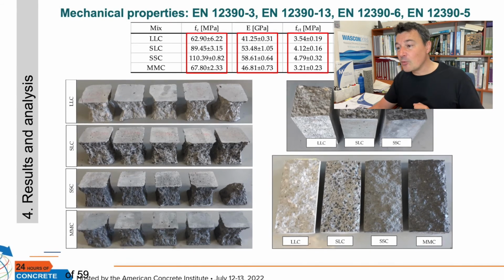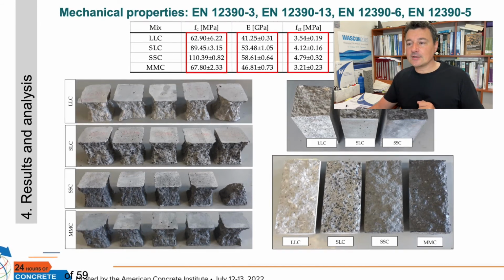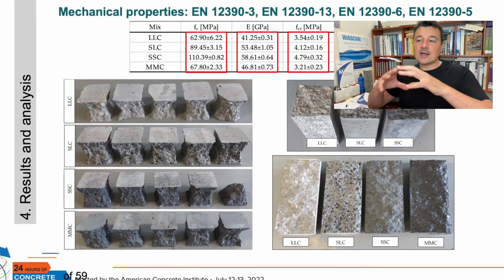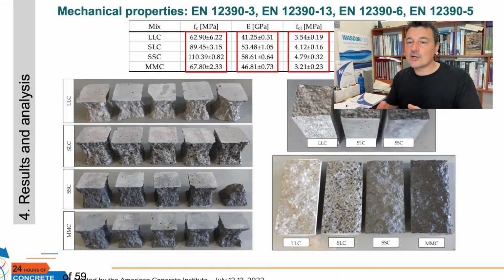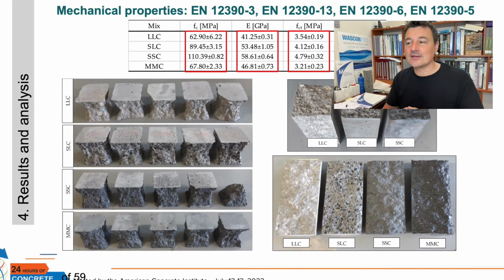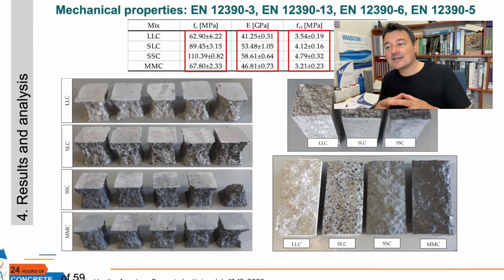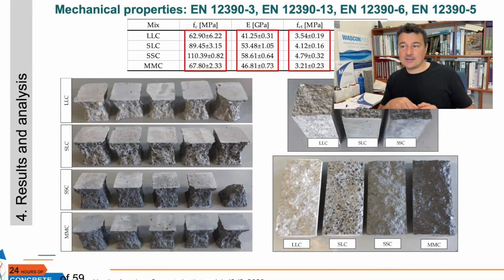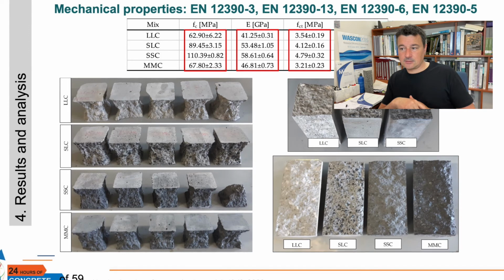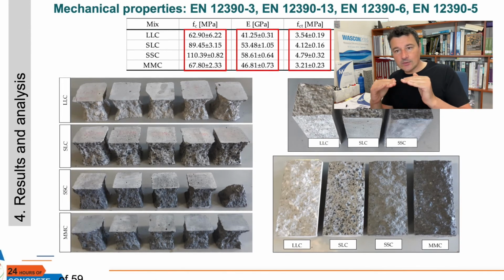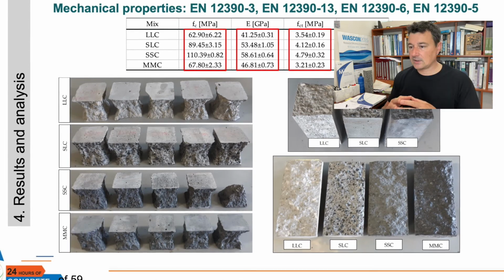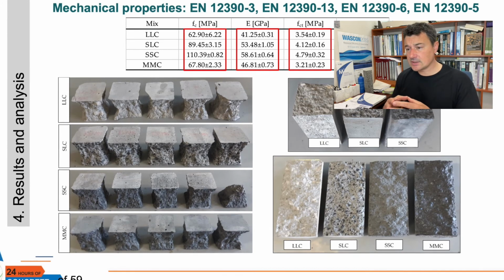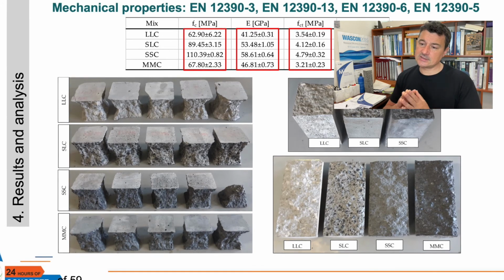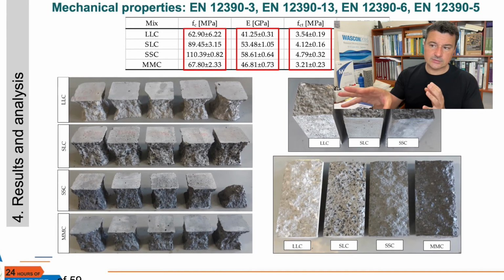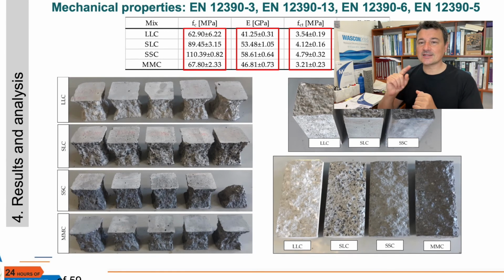Also, the elastic modulus is very high. In this case, in the total siderurgical aggregate concrete, the modulus of elasticity is near 60 gigapascals. And also, we can increase the flexural strength. Here in the pictures, you can see how the material is after testing. All of these results are obtained at 28 days.